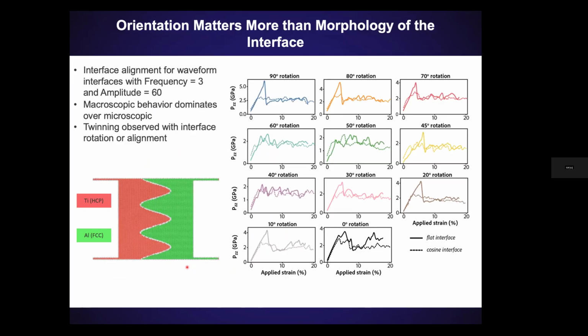What about the other thing we were seeing? In that flat interface, we would see a lot of sliding between the materials, especially as you were rotating and pushing them; one material would slide with respect to the other. But when you added that rough geometry or shape at the interface, you lock in those interfaces and basically stop the sliding behavior. You see a lot more twinning in the material as compared to the flat interface. Here are the stress strain responses for a flat interface versus a cosine interface as a function of that rotation. At 90 degrees the behavior is different, but eventually, if you keep rotating, they both start behaving very similarly.